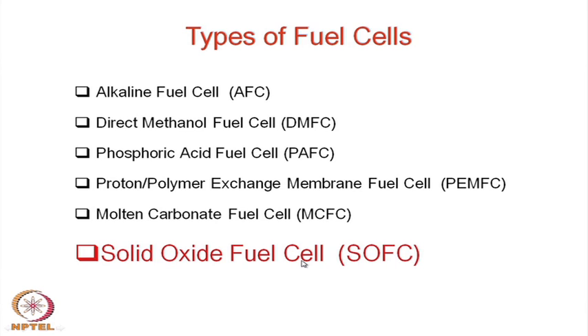Originally, it used to operate around 900 to 1000 degrees centigrade, primarily because the electrolyte zirconia does not have very high ionic conductivity, or the overall conductivity is relatively low. So, sufficient conductivity is obtained only at a higher temperature. Okay. So, that is the reason the operating temperature is highest among all the fuel cells listed here. Of course, research is going on to reduce the operating temperature. We will look at it. So, this is an all solid state fuel cell and all ceramic fuel cell. So, all the components are ceramic components, and they must withstand fairly high temperatures. So, our topic of discussion will be concentrated on the solid oxide fuel cell.